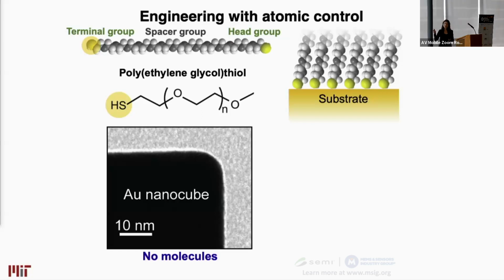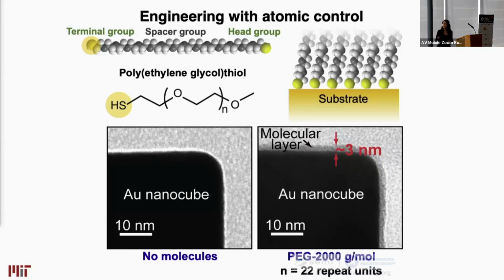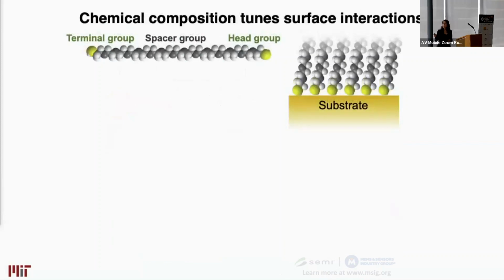So this is a transmission electron microscope (TEM) image of a gold surface without any molecular layer. Here I'm showing you the surface functionalized with a 3 nanometer thin PEG-thiol molecule. Now, through the choice of the molecule, you can very precisely tune the thickness as you wish. Another advantage of molecules is that you can change the composition so that you can tune the surface interactions.